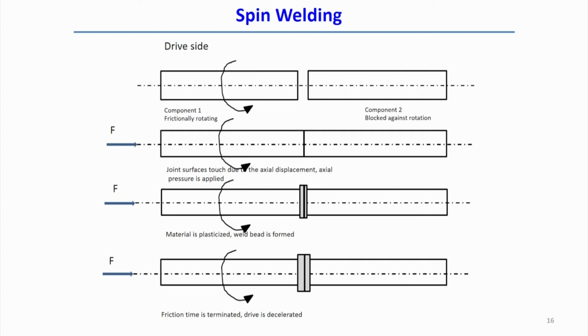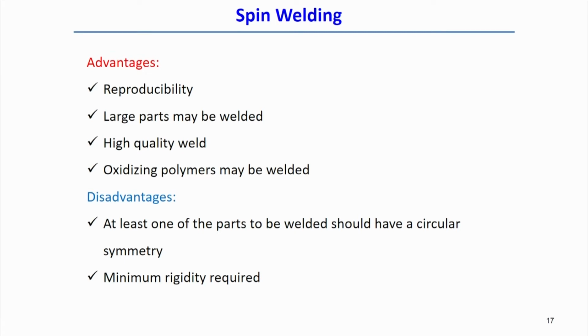So, we can find the flash formed at the joint interface. It is a similar kind of technology to that in conventional welding processes, that is the friction welding process. This is the principle of the spin welding process, but the main advantage of this process is reproducibility, that means reproducibility with similar welding conditions, and large parts can also be welded, and high quality welds can be achieved, and oxidizing polymers may also be welded, because if oxidizing polymers form an oxidized layer, it can be removed in the form of flash from the outside of the joint interface.